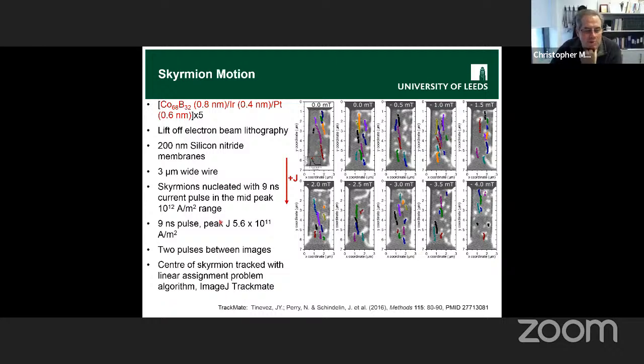And then we could apply these somewhat weaker pulses. Here they're 9 nanoseconds long, and they're about half a teraamp per meter squared. We would take an image like this, and then we'd apply 2 of these pulses, and then take another image and see what had happened. Quite a few of these skyrmions would have moved a little bit. As you repeatedly apply pulses, you can track out their motion, and that's what these sequences of colored dots are. Each one is a single skyrmion that's moved down the wire. So this is at 0 field.